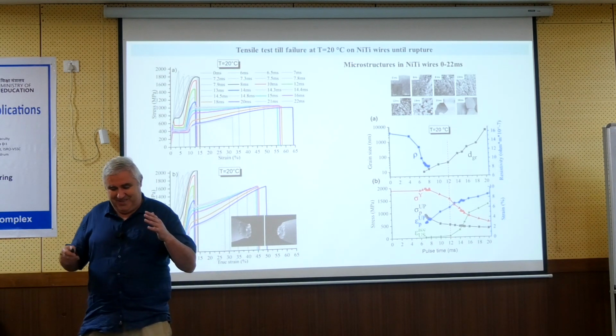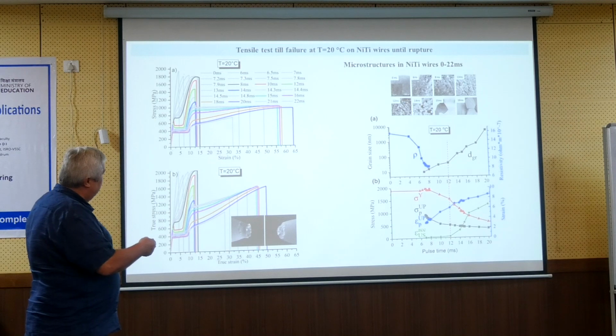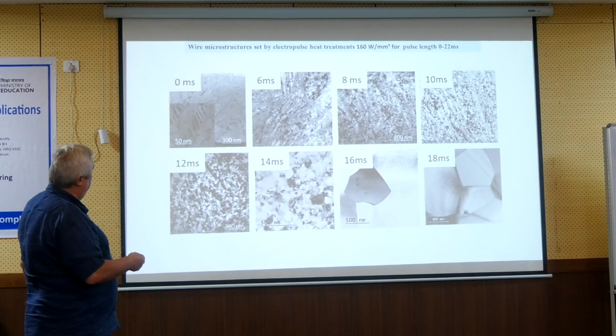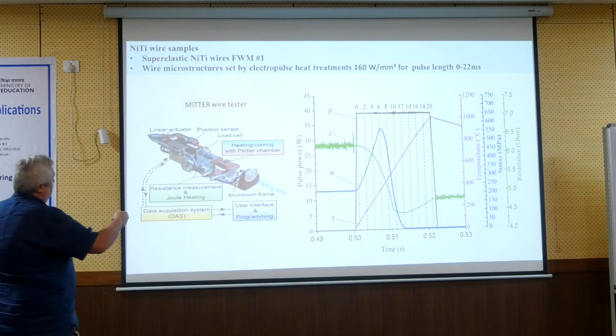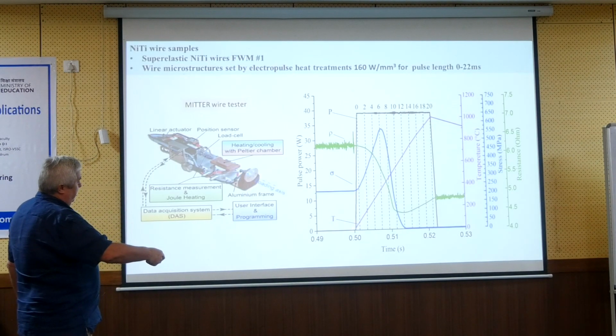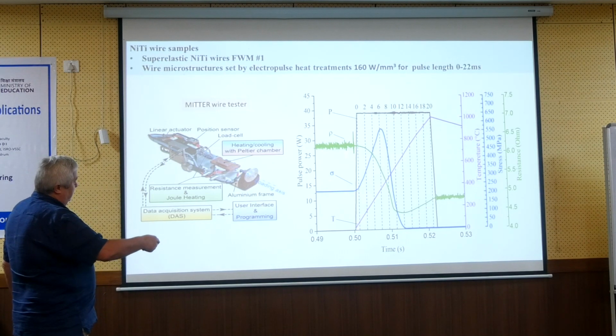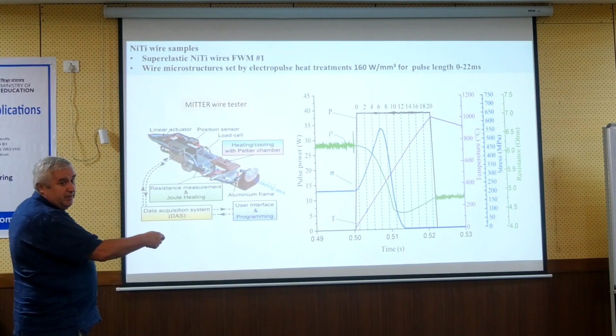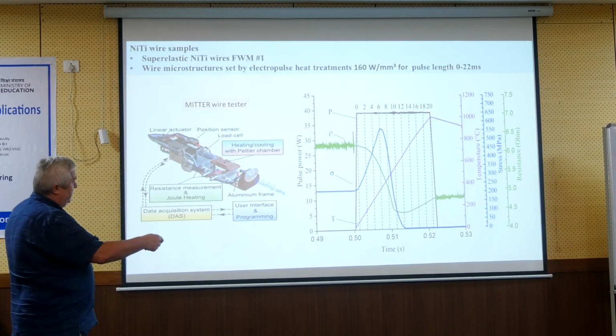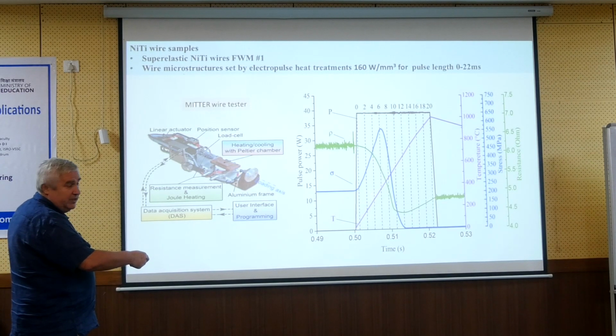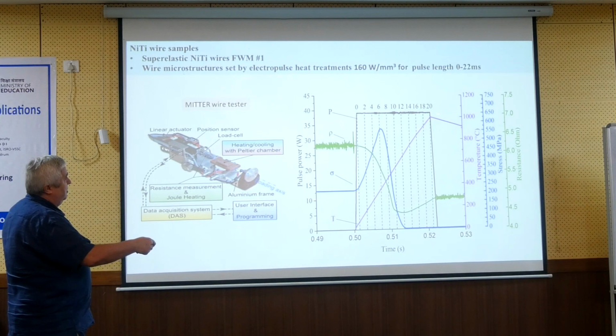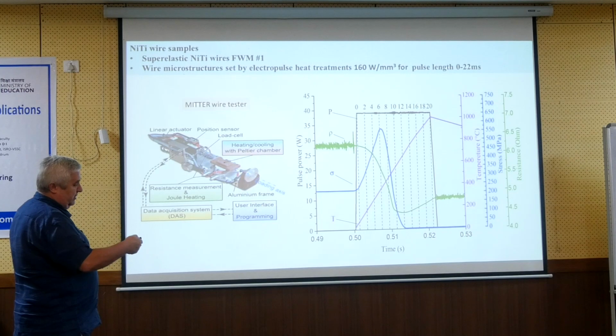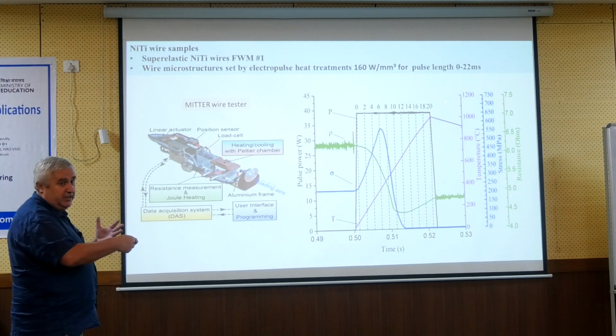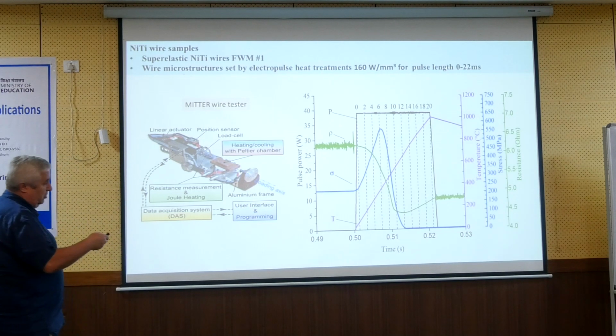Okay. So again, this is important that you understand. We heat the wire by electric current. So this is the electric power pulse. This is the maximum power, and this is the length of the power. The length is in milliseconds, 2, 4, 6. Depending on the length of the power, you will have a maximum temperature, because after 20 milliseconds it switches off. So we reach a temperature of nearly 1000 degrees. But this is only calculated through the heat equation. We cannot measure this temperature. So it is a so-called estimate.